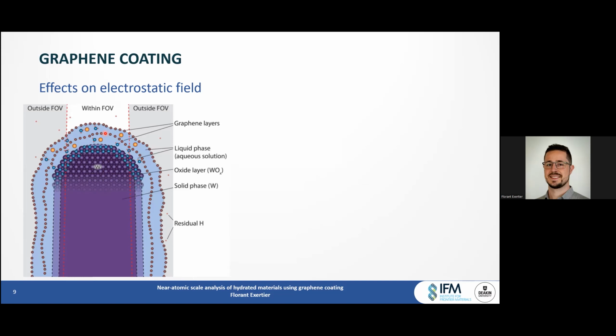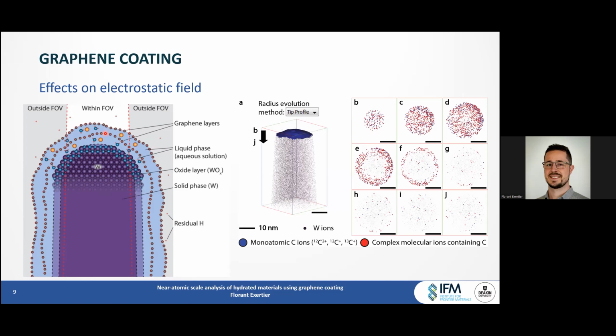And this is what the 3D reconstruction of such a tip looks like. So these images here come from successive 2 nanometer thick cross sections, and we can clearly see the graphene draping the tip of the specimen, as highlighted by the rings coming from the successive cross sections. So several samples were coated in this way, with varying numbers of graphene layers in order to study the impact of multiple layers versus one single layer on the electrostatic field.